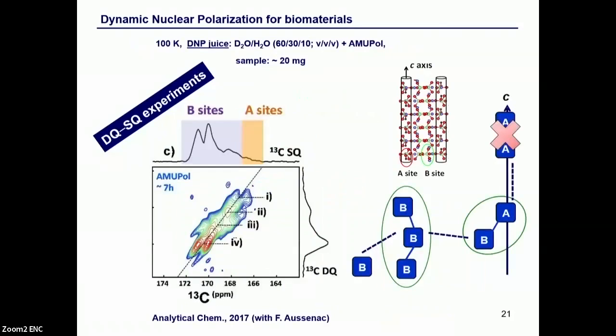The second reason is that, again, due to the huge gain in signal-to-noise ratio, by using DNP, you can very quickly record double quantum, single quantum experiments. Here, I focus on a very complex problem, which is the substitution of biological apatites by carbonates. There are two sites which are possible, the A site corresponding to the OH groups and the B sites corresponding to the phosphates.